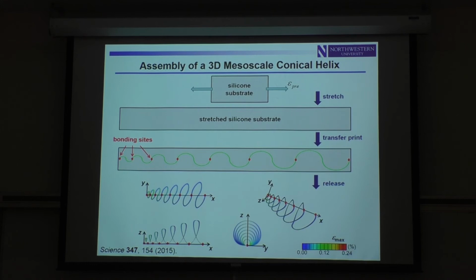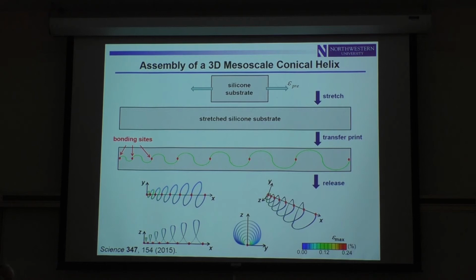And so, with this kind of system, now we relax the strain, the pre-stretch in the silicone substrate, so it rebounds back to its original length. And in doing so, it applies compressive stresses to this structure. Beyond a certain threshold, the unbonded regions, which are just interacting with the substrate through van der Waals interactions, will delaminate and move up out of the plane and translate and twist in a way that's defined by the pre-strain, the geometry of this filament, and the positions of these bonding locations, which for this particular case induces a geometry transformation from this planar serpentine to this 3D conical coil, as I'll show you in the next